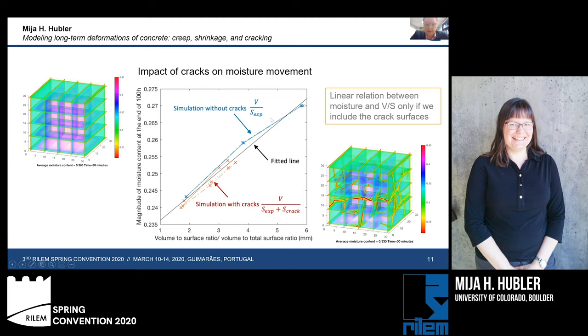However, if we introduce these cracks into our model, the only way that we can make the same relationship is if we consider not only the external surface area of our cement sample, but also the additional surface area introduced by our cracks. So the first point here is that in order to correctly capture the effect of the cracks, we need to somehow capture the surface area being added due to these cracks, which act as highways for our moisture to enter our sample.